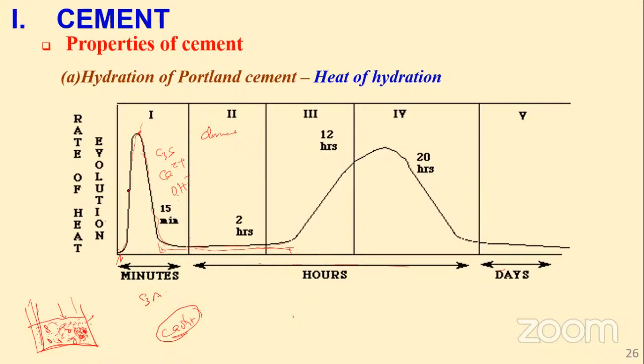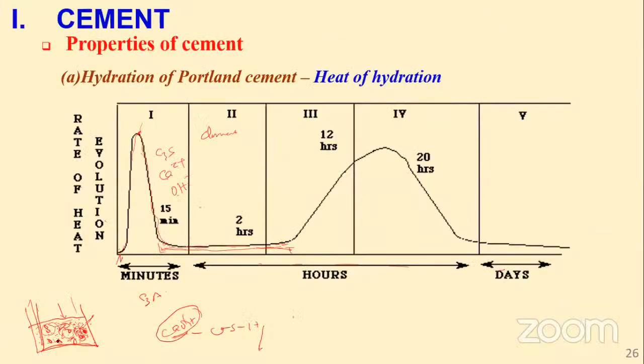I was saying, think about everything being suspended in this mix, okay? So when too many of the hydration products are formed, they surround the unreacted particles. Therefore, it takes time for the water to reach those particles for them to hydrate. That's why the heat goes down. But upon accumulation, as calcium hydroxide is formed, calcium silicate hydrates are also formed. And what happens? These silicate hydrates precipitate. They settle on the bottom.